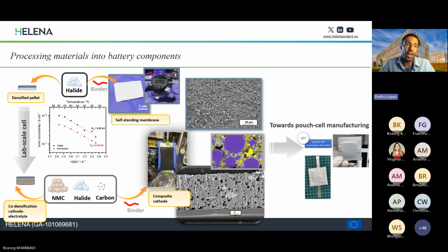And so, as you can see, we've been able to move from very thick densified pellets to self-standing membranes of around 60 micron, already having quite good ionic conductivity. Of course, it decreases with respect to the halide pure material because it has some non-conductive materials such as the binder. But it's still having conductivity beyond 1 millisiemens per centimeter, which is required for high power applications. So that's on the side of the halide electrolyte.